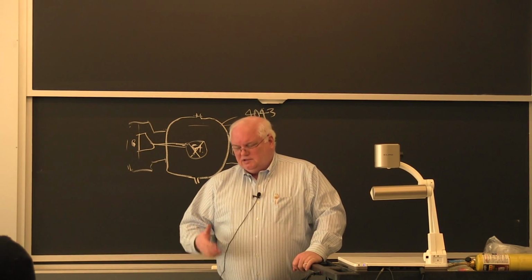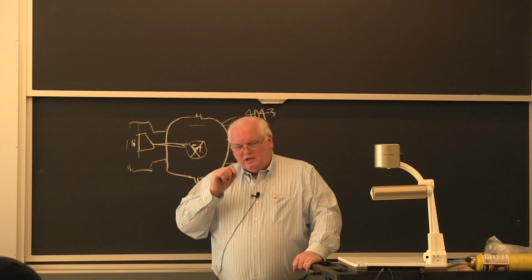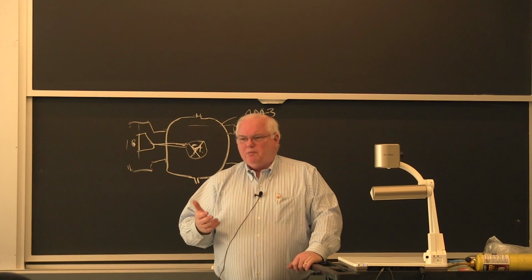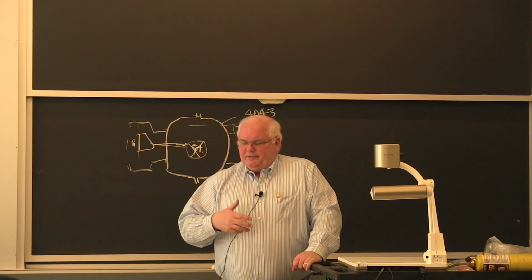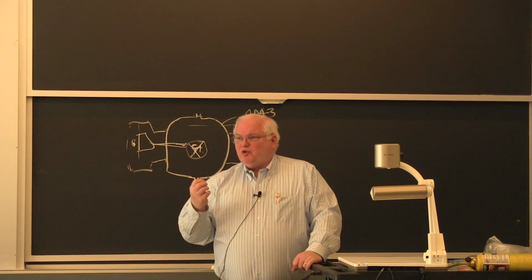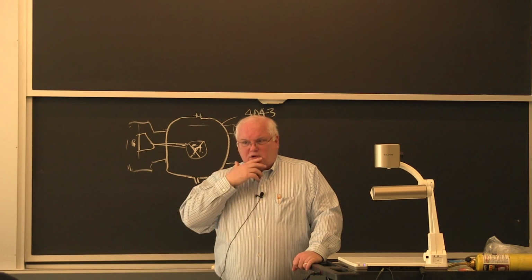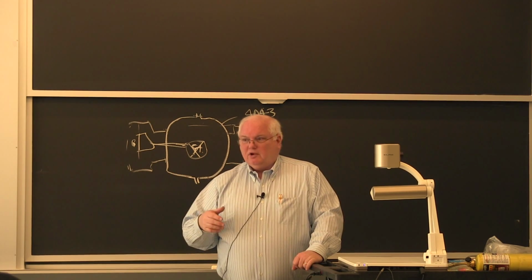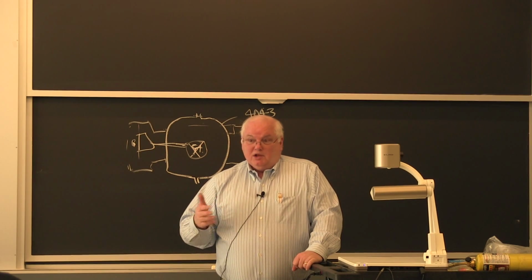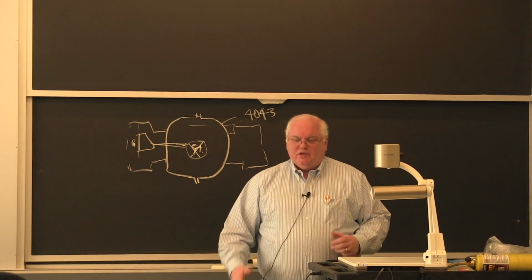So I said, okay, well, John, sit down, tell me what your problem is. And he told me that they wanted to cut the tissue they wanted to cut, they didn't want to burn through beneath that, and they didn't want to reflect. And I said, well, you're posing a problem that is sort of betwixt and between. To have an absorptive material, you want something with no free electrons, because it's the free electrons in a material that re-radiate the energy and cause it to reflect. I mean, what are the best mirrors? Silver, gold, copper, okay? They have lots of free electrons. But if you want something with good thermal conductivity among the metals, you're talking about something that has lots of free electrons. Silver, gold, copper, okay? So he was actually looking for two things.